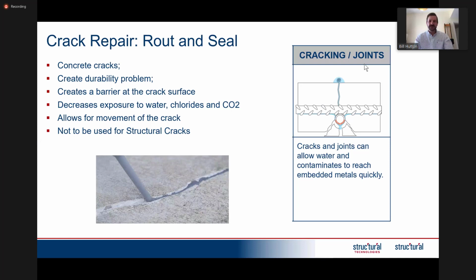Someone said this the other day actually, that there are three things in life which are guaranteed. The first one is death, the second one is taxes, and the third is that concrete will crack. So unfortunately, yes, concrete will crack. If your concrete has cracked, then where the steel is passing through the crack, there is no protection. So if the cracks are not repaired properly, then what starts as a crack can quite quickly lead to a durability problem, which can then lead to even a structural failure, even a failure of a particular part of a structure.